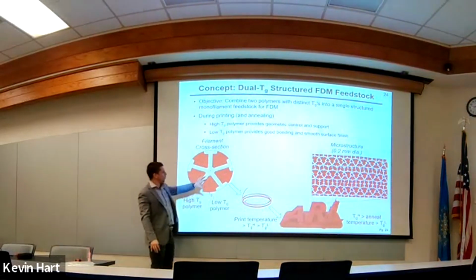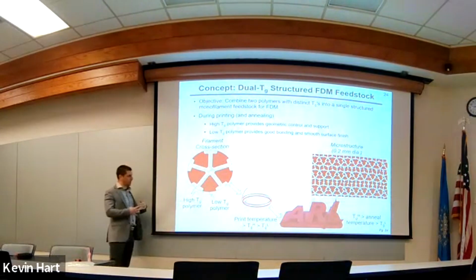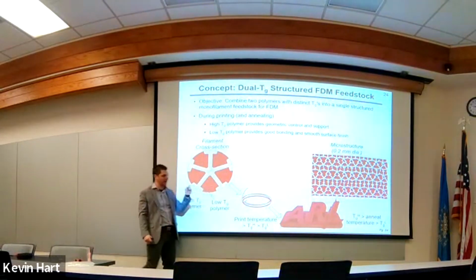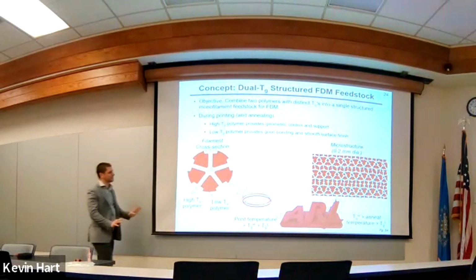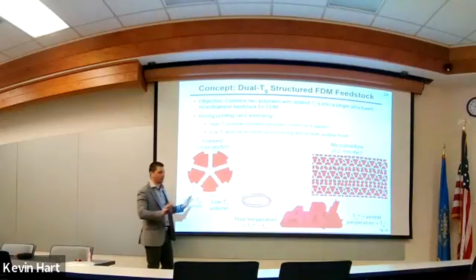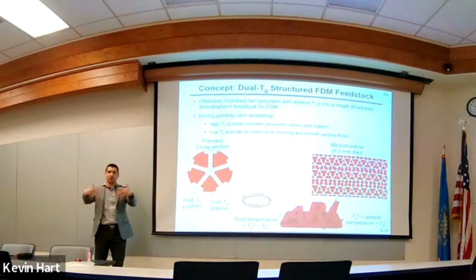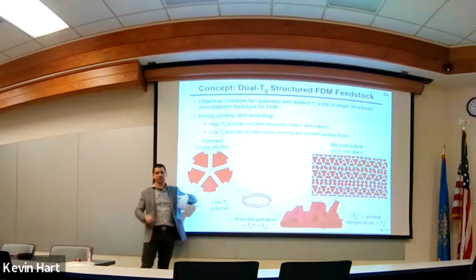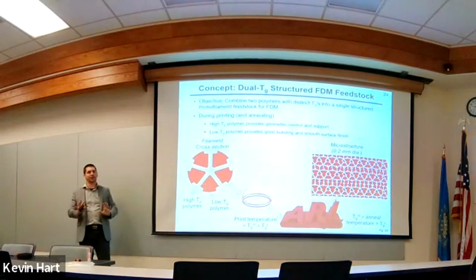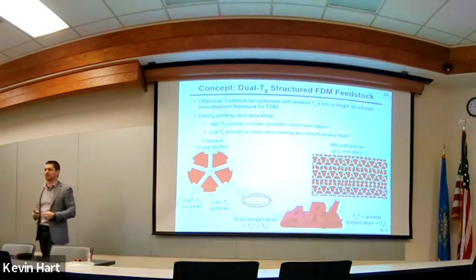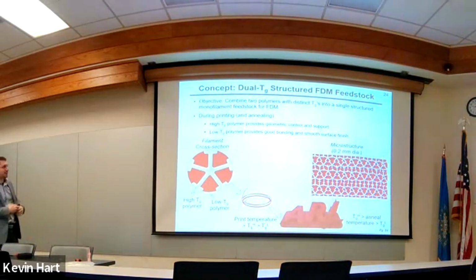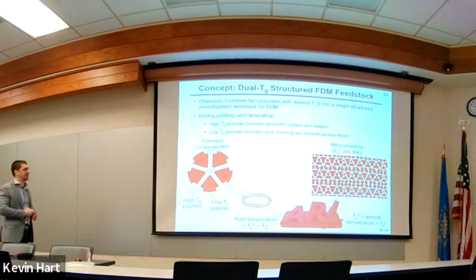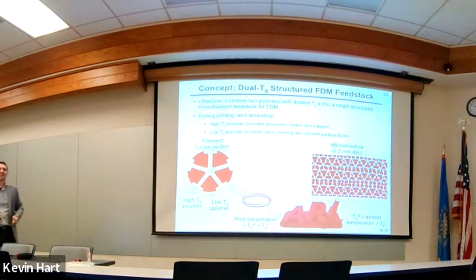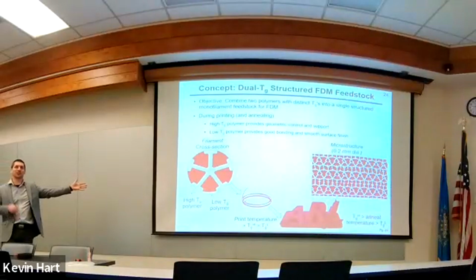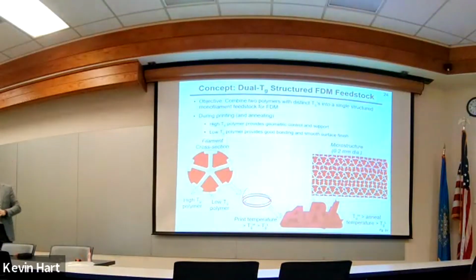And the idea here is that we're going to now anneal this thing at a temperature between the glass transition temperatures of the white polycarbonate and the red ABS. So the annealing will be such that the red ABS will flow and do all that wetting and reptation and all that good stuff that we want, that healing of the interface. But the white will just stand strong and be a skeleton, so that it doesn't deform during the annealing process, right? It's like your backbone, your skeleton, that doesn't deform during the annealing because you're not annealing above its glass transition temperature. Okay, it's the general idea. But this filament doesn't exist. Okay, so we have to figure out a way to make this ourselves. All right. There's not a lot of dies that exist for a traditional barrel extruder that could make something like that. Okay, so we got to do something else.